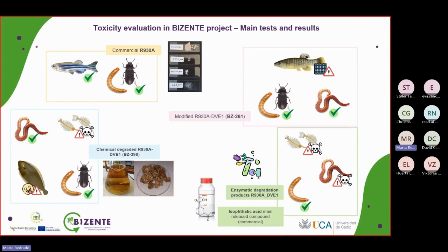Here you can see a small summary of what we've achieved so far. As I mentioned, R930 is the resin that gave the best results in the enzymatic biodegradation. So the toxicity tests have been carried out for the whole family of these resins, starting from the commercial resin to the released products like the isophthalic acid.